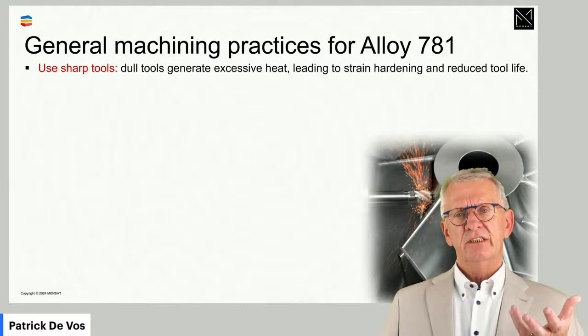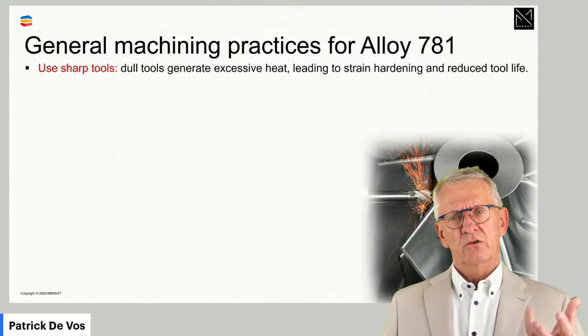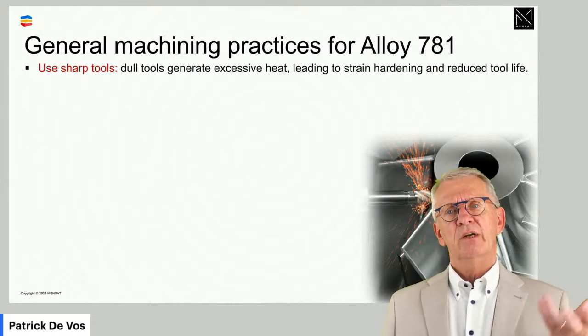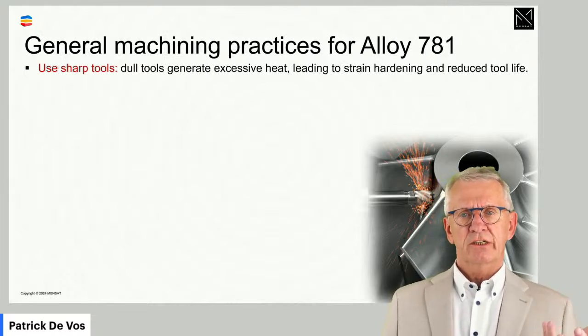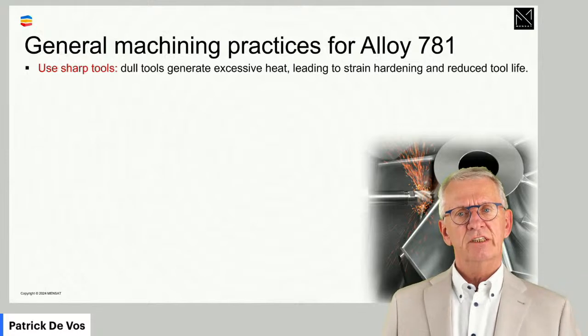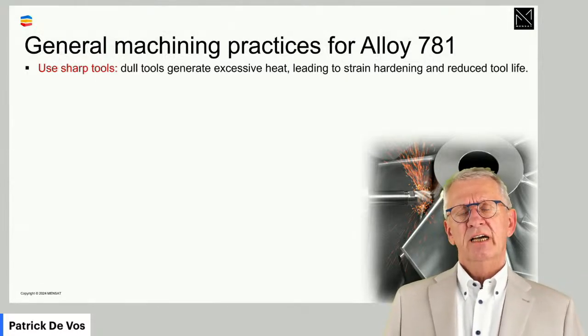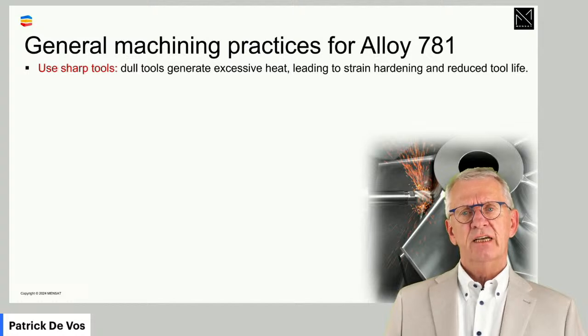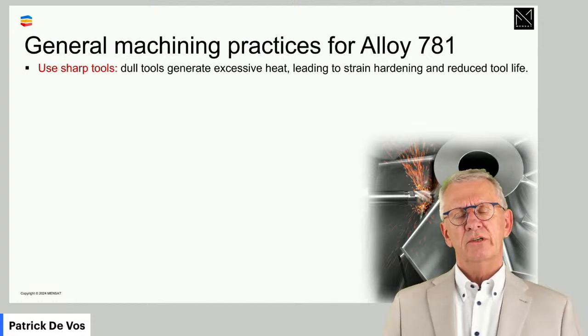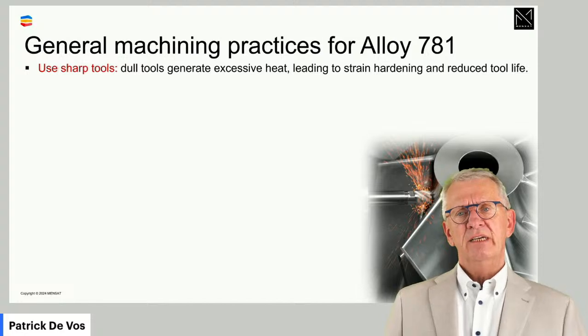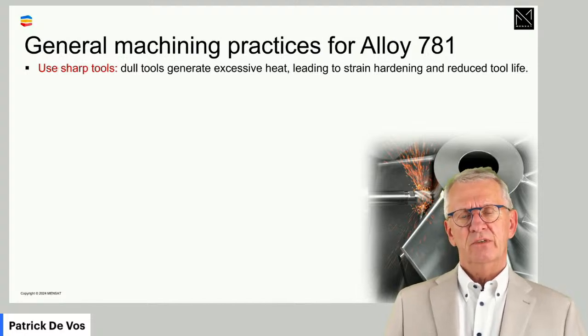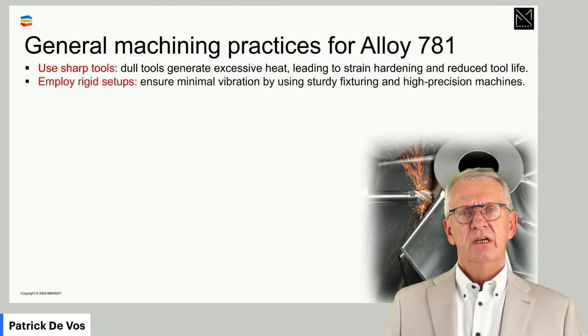The main reason is to minimize heat generation, because superalloys show a rather low thermal conductivity. So if you generate too much heat, there will be too much heat concentrated in the cutting zone, and that has negative consequences. The other thing is that a positive acting cutting edge creates less deformation before it's cutting, and that means that the strain hardening effect will be less present during the operation.